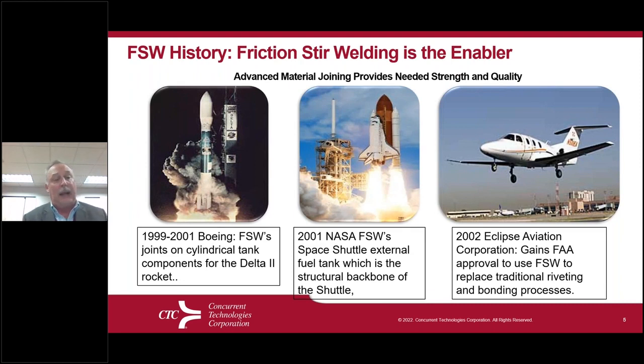Some of the history here, some of the early applications: Boeing adopted this for the Delta rocket fuel tanks back in the late 90s. The space shuttle external fuel tank was adopted for friction stir welding in the early 2000s, as well as Eclipse Aviation gained FAA approval to apply it to airframe structures in the early 2000 timeframe. Almost in all these cases, what they were looking for was the benefits of some new advanced alloys of aluminum, namely the aluminum lithium alloys that could not be fusion welded. And so the friction stir welding was able to bring that high strength material into the application for space and aerospace applications.